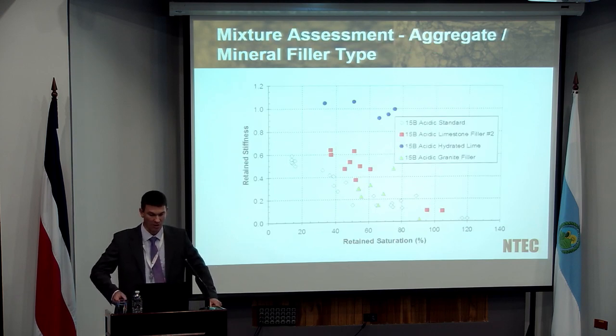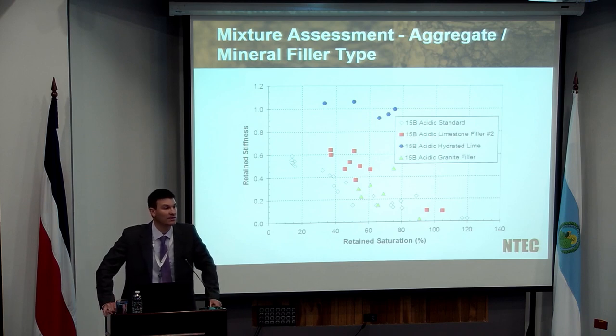We also obviously were aware that one of the key drivers in terms of moisture performance is a function of the aggregate or the filler type. So although the binder plays its part and we can mitigate some forms of moisture damage by changing something to do with the binder chemistry, or potentially adding a modified binder, in other words, a polymer modified binder, we know that the key driving mechanism in terms of moisture damage is usually linked to the aggregate and increasingly also to the mineral filler. So this was data generated on a test, which I will describe as soon as we get